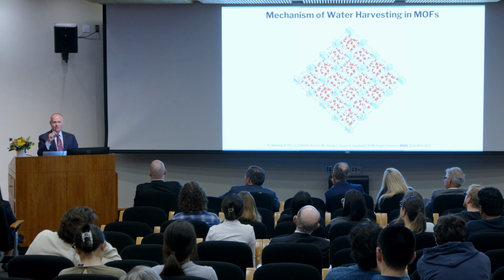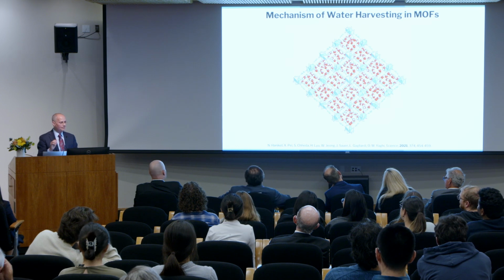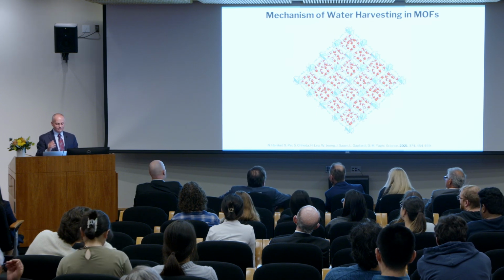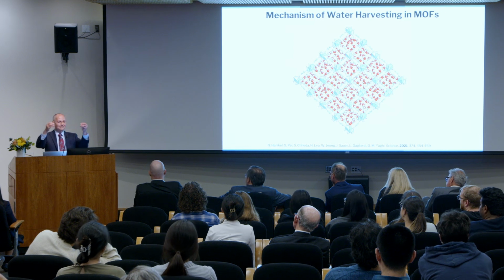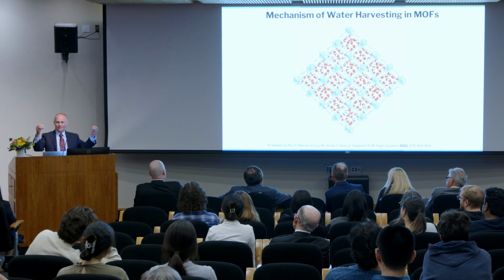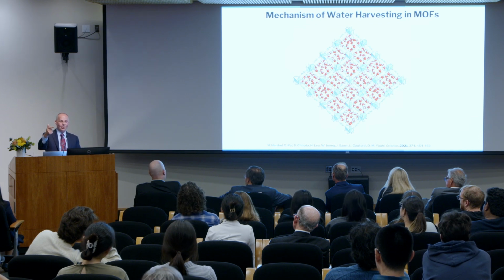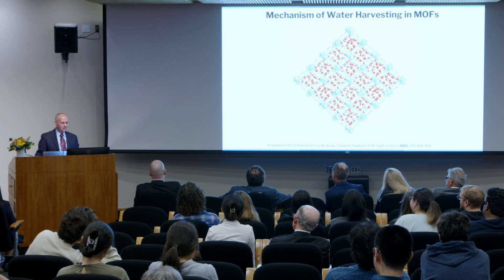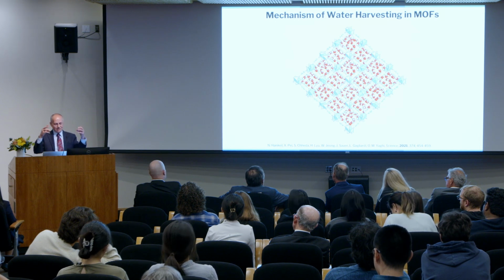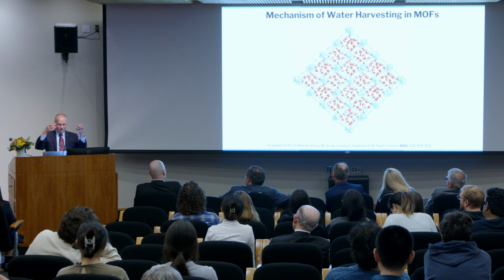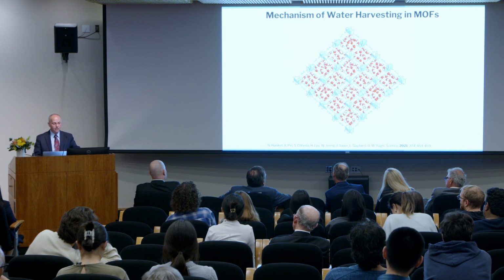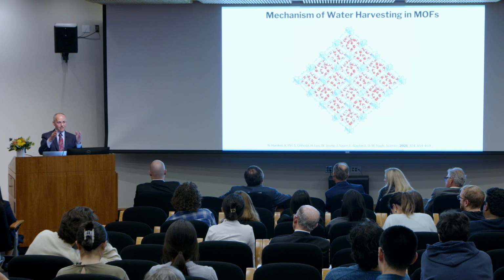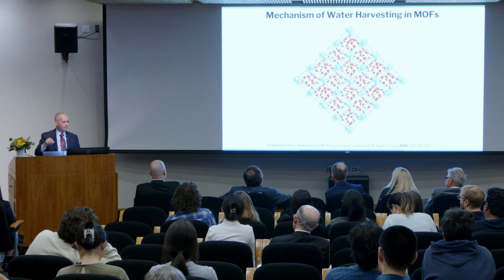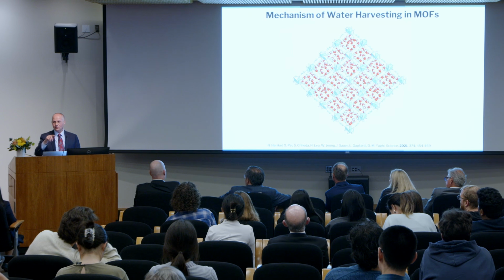Now we can go back and say, okay, I'm happy with this MOF, but I want more water. What should I do? Well, you say, well, Professor, you can extend the linker and make larger pore. Well, that's true, but that doesn't guarantee that that MOF is going to form or is going to be stable, right? So we did that. We expanded the pores by using longer linkers to have more water. You can't expand them infinitely because after 20 angstrom, you start getting double step isotherm. That's not very efficient. So you are limited within that 20 angstrom thing.